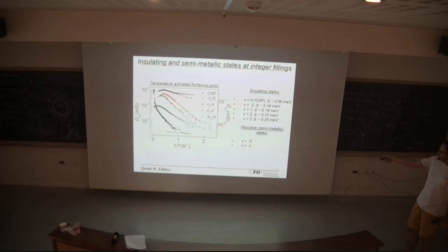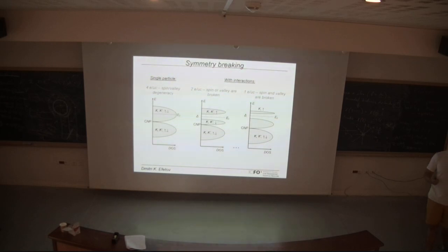For some of these resistance peaks, we actually don't observe temperature activated behavior. This could be because the gap is too small, or the other possibility is that the interactions are not strong enough to open up the full gap, but are just leading to some sort of Dirac-like semi-metallic transition. These are all possibilities from theorists. So for the -1 and -3 states, we don't observe an entire gap. And what we think is happening is that we went from this picture to this picture, where we are now able to observe insulating states for every integer of electrons per unit cell, where we now start to get some bands where valley and spin might be broken at the same time.